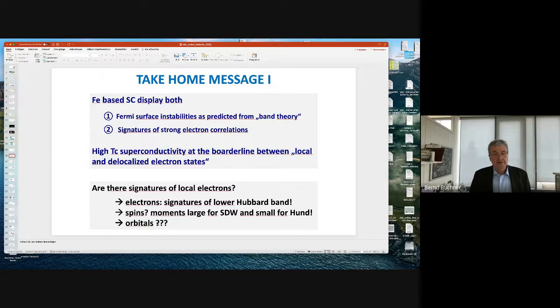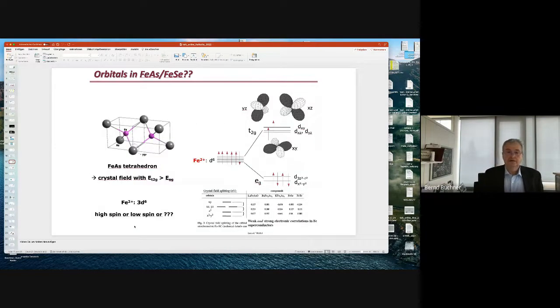And the next question then, what about orbitals? What do I mean with orbitals? So we have this iron atom surrounded by four arsenic or four selenium atoms. And if this would be a local state, let's assume that would be a localized insulator, then of course we would have a crystal field acting on these originally degenerate iron d orbitals. And in this kind of geometry, it's known that the eg orbitals, so those which are relevant for the cuprates, the d x squared minus y squared and the z squared orbitals, have a lower energy. And the t2g orbitals, named xy, xz, yz, have a higher energy. That's a typical crystal field splitting, and that's also expected for these iron arsenide layers.